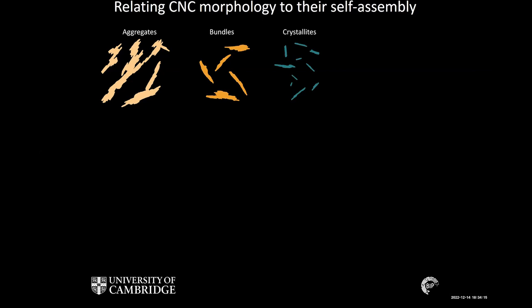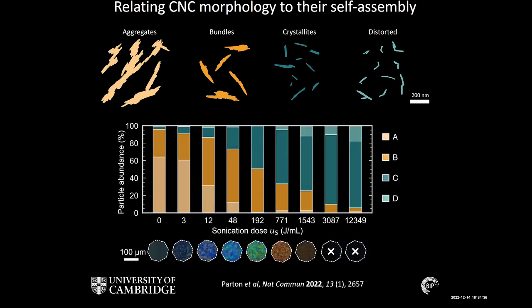And we also found a population called distorted crystallites, where it appears that the crystal has been kinked or broken along the chain axis. And you can see that we chose these names so that they would neatly spell out A, B, C, D. And so by looking at electron microscopy images for a wide range of samples, I was able to quantify the relative amount of each type of particle, A, B, C, D, as we increased the ultrasonication dose. And what we see is that there is quite a natural progression from A to B to C to D. Initially, when we have no sonication, our sample is mostly aggregates.